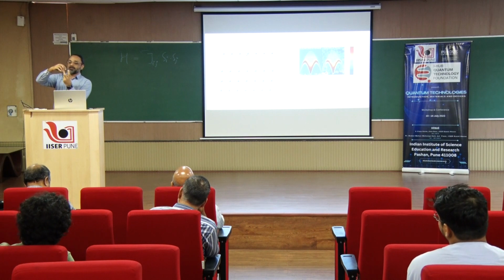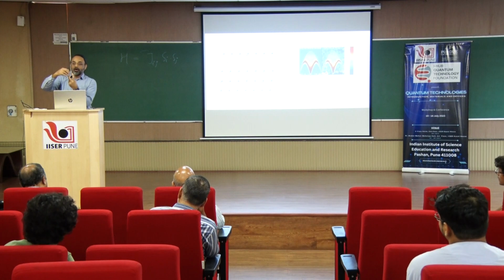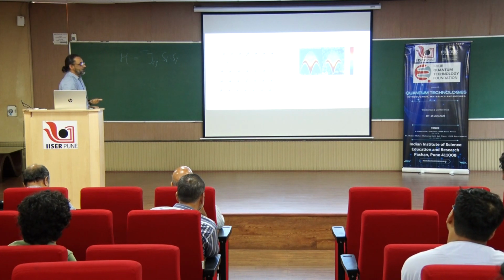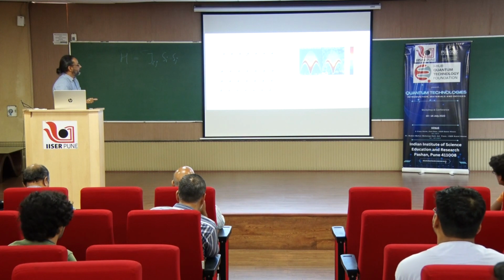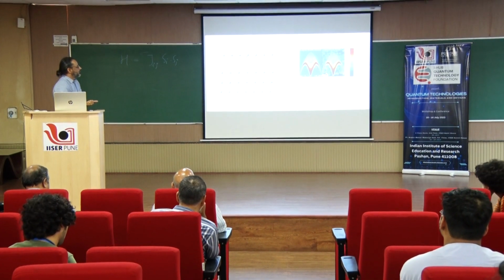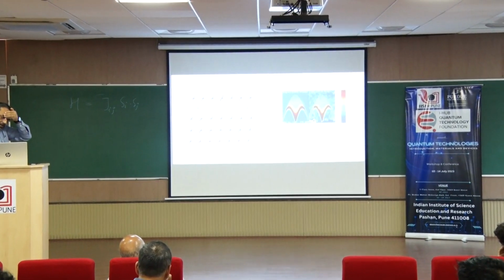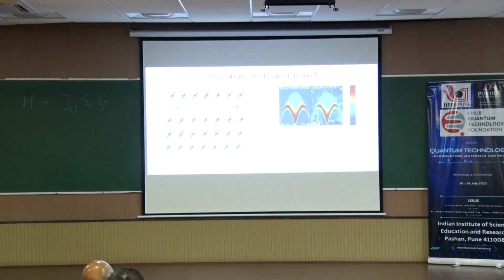What that means is that all the energy can be taken by one of the spinons, and the other may not take any, or they may divide it equally between them. So what that means is that you get a continuum of states. Here you see this continuum, which has a lower bound as well as an upper bound, and this continuum in inelastic neutron scattering is one of the hallmarks of a spin liquid.